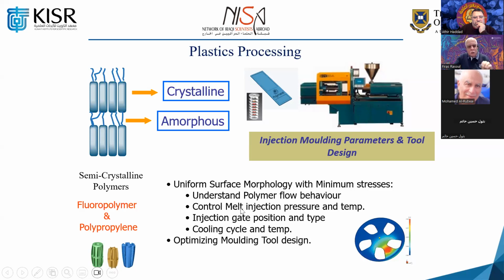Also try to control the melt injection pressure and the temperature, and the gate position, where the injection is happening. You don't want it in an area where there is going to be a lot of stress. There will be a lot of polymer grafting on that. So try really to put it in a position which is almost hidden, so you will not affect the performance of your parts.